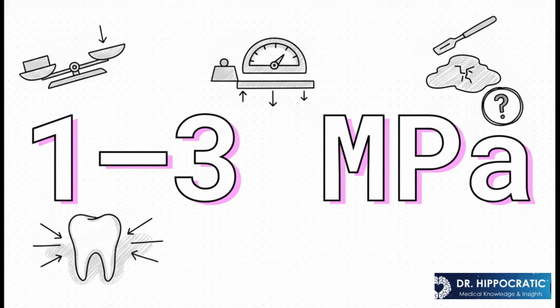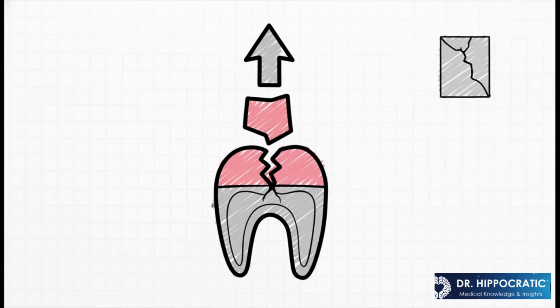But here's a little twist. Even with the absolute perfect surface prep, the bond strength is only about 1 to 3 megapascals. Now, a megapascal is just a unit for measuring pressure, but for dental materials, that number seems kind of low, right? And, well, it is. It's surprisingly weak, which makes you wonder, why are we even using this stuff? And this is the real secret. The problem isn't the bond. The problem is the GIC material itself.